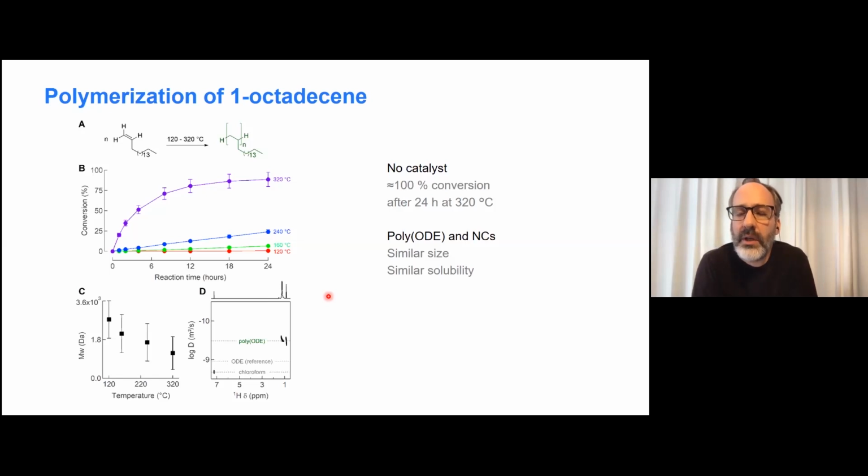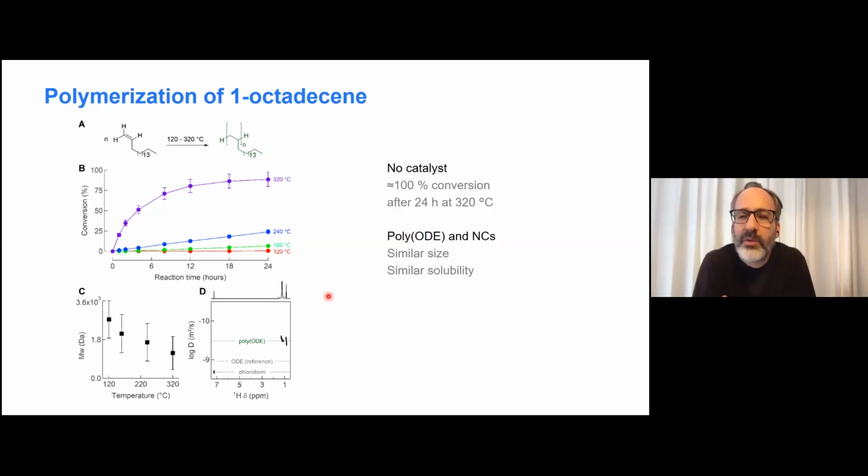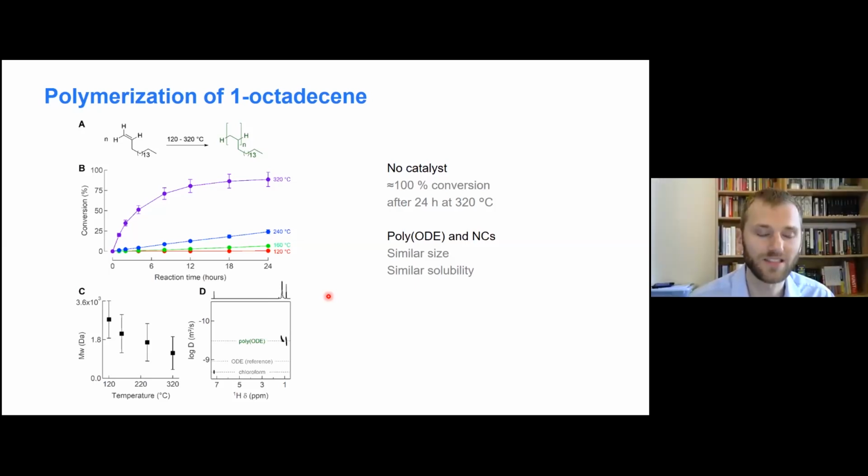I don't know what the answer to that is. So you studied that. If there's trace left after you purify them, and that's why we all spend all this effort trying to purify our nanocrystals and get rid of these organics, as you say. But now you know the source of this. Okay, I have two answers to that, but I have to be very careful. The first one is that yes, I know of people that use methyl acetate as the non-solvent, and I've seen their NMR spectra, and it looks like they got rid of most of the polymerized octadecene.